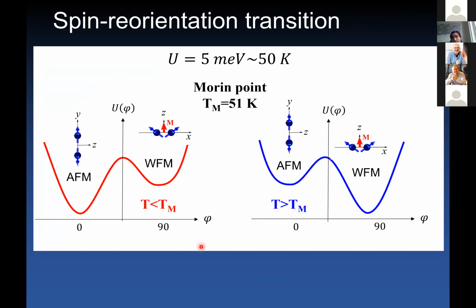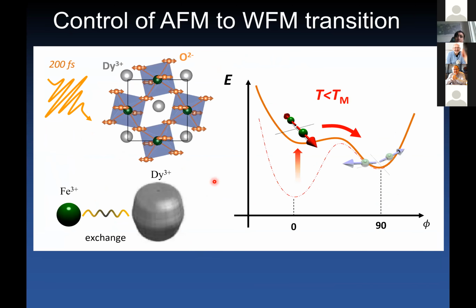And being a first order phase transition, it is characterized by a competition between two energy minima, one corresponding to a collinear antiferromagnetic arrangement and one to a non-collinear weak ferromagnetic arrangement. So by changing the temperature, you can favor one phase versus the other. What we wanted to do in our experiment was to sit at a specific temperature and manipulate the crystal lattice on very fast timescales in order to change the magnetic potential and favor one phase over the other.